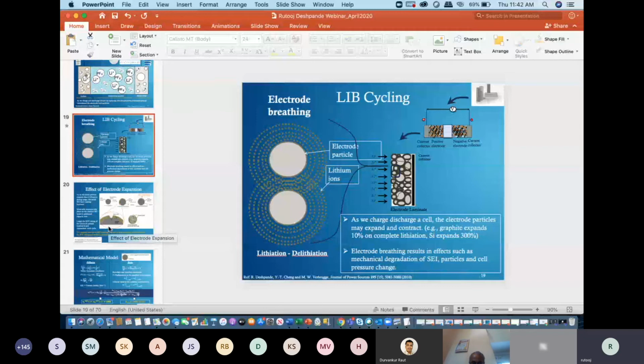Again, the life of your battery is totally dependent on it. I mean, the SEI layer is the key of battery life. So if you know the right additives, your cell can last longer. Even at higher temperature, I have seen cells which are performing better at 45 degrees Celsius than at 25 degrees Celsius in storage. That could be just because the additives are such that they react quickly at 45 and form a good layer around the electrode particles.